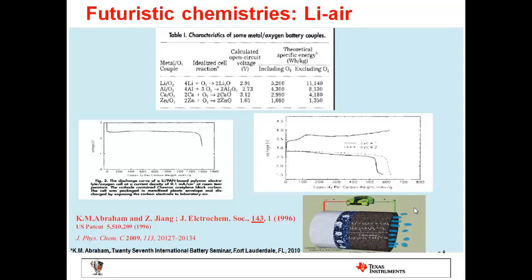And the way to concentrate it is to use pretty expensive catalysts, usually platinum, iridium, that absorb some amount of oxygen on the surface. So the reaction rate is pretty slow. That means you cannot deliver much power from these systems. It is still acceptable for applications like hearing aids, where not much power is needed, but it has to operate for a long time. So I expect lithium air will first appear also in hearing aids, but it will be not rechargeable.